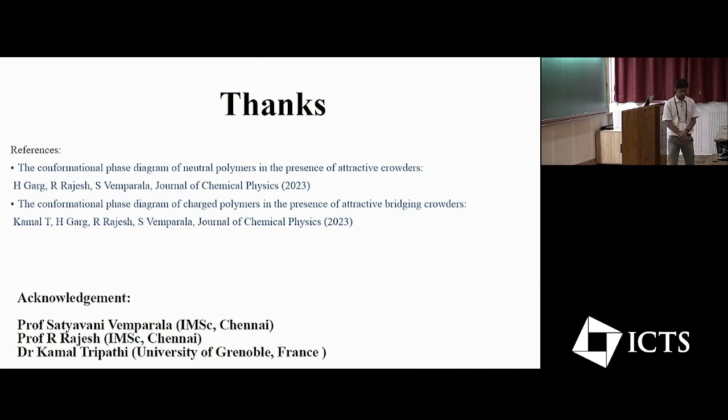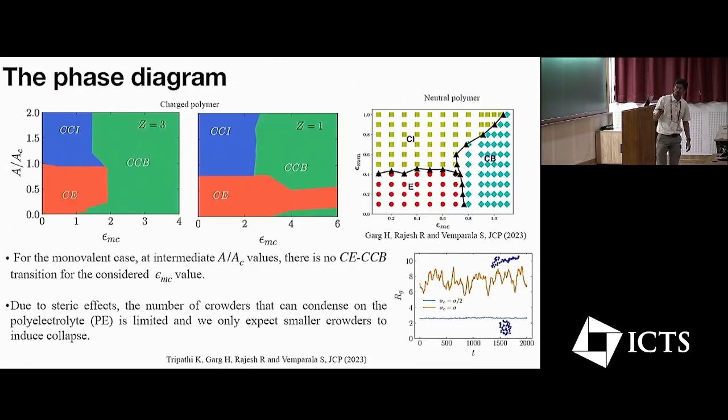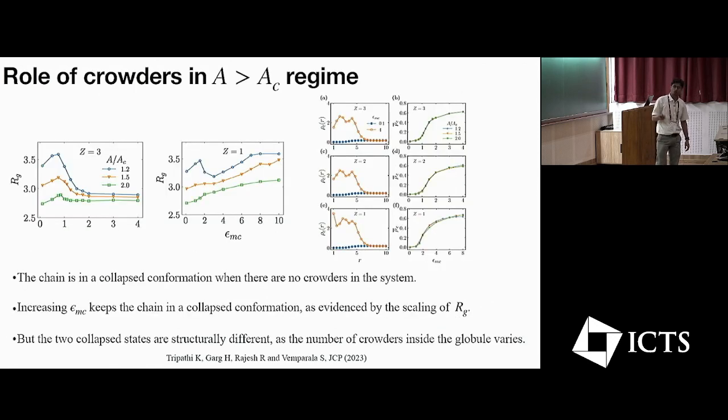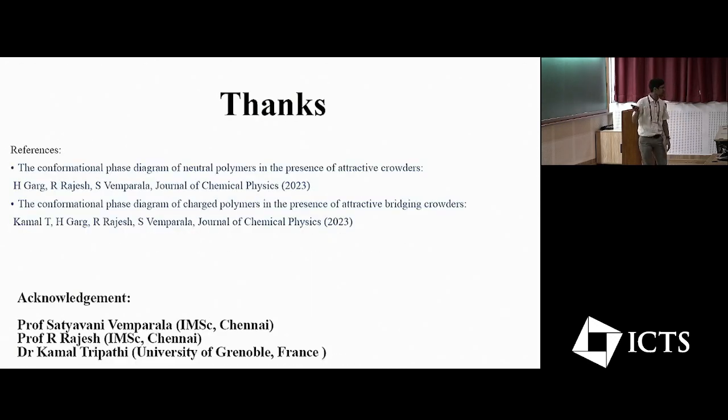Yes. So these are totally flexible polymers, there is no persistence length as such. But we also looked at the regimes that I showed in the first slide, that Rg goes as N^(1/3) with the monomers in the poor solvent. So all of them, what we are calling the poor collapse regime, we scaled with the different monomer sizes, and these all collapse onto the single curve. You can find these in the manuscript itself. All of them are scaled with the 1/3 exponent for a poor solvent condition. Any other questions?